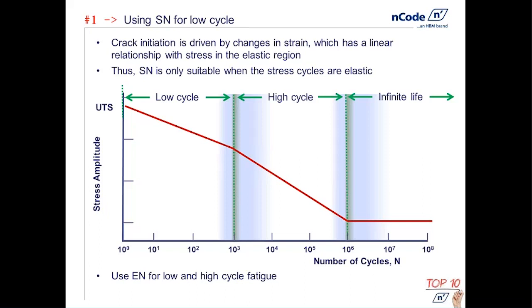There are a number of occasions where we see users using the stress-life methodology for the low cycle region. This would be regions where we start to see plasticity occurring in our hot spots and the cycles to failure are going to be fairly low. Mathematically there's nothing that prevents us from extrapolating this curve back into the low cycle region, but it is unlikely that you're going to get a reasonable and accurate damage result by using this particular approach.